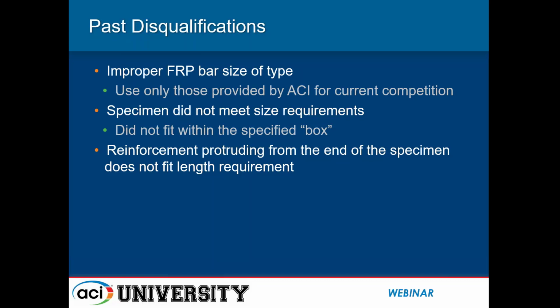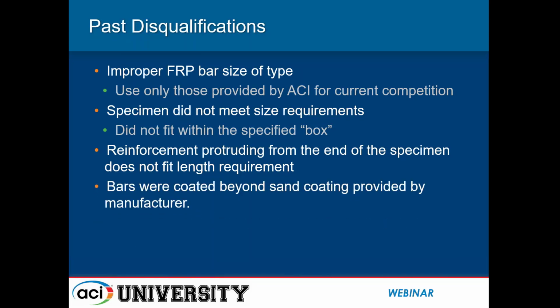Please know that the manufacturers of the reinforcing bars have cut their bars to an approximate length. Do not use the bars at these lengths without verifying that they meet the length requirement of the competition. It may mean that you need to cut the bar down slightly to meet the length requirement. Bars were coated beyond the sand coating provided by the manufacturer. Again, you may not use other materials to enhance the bond of the bars with the concrete surrounding them. The specimen was too light or typically too heavy. Again, I've mentioned this previously, but you really need to verify the weight of your member prior to arriving at the competition. You will not be able to modify your specimen once you are at the competition site.